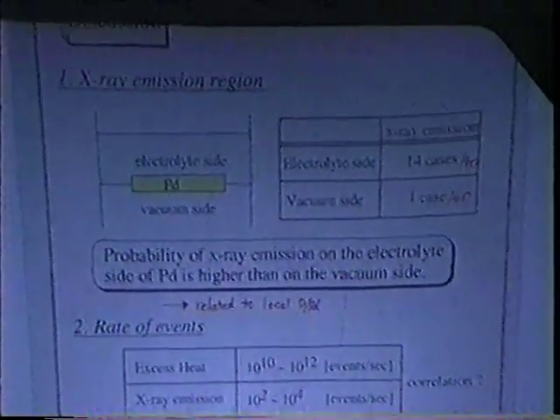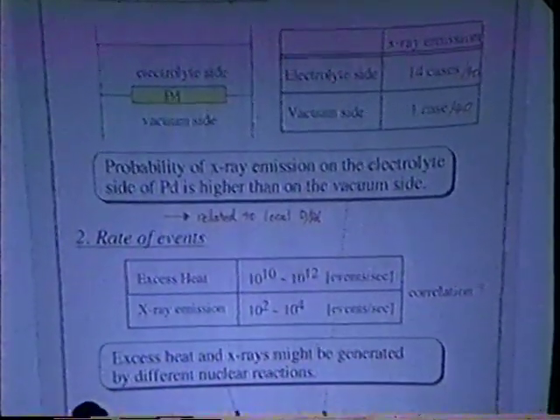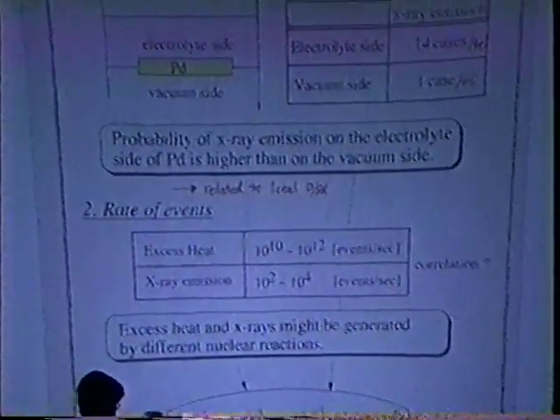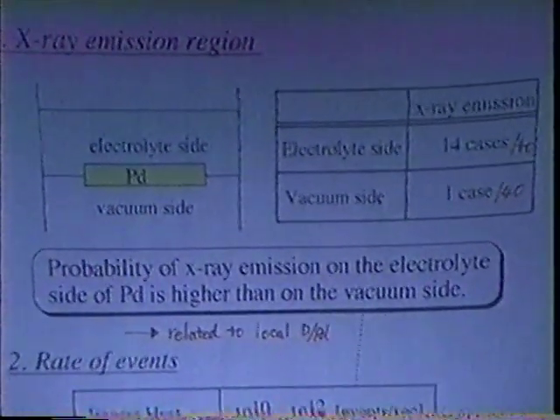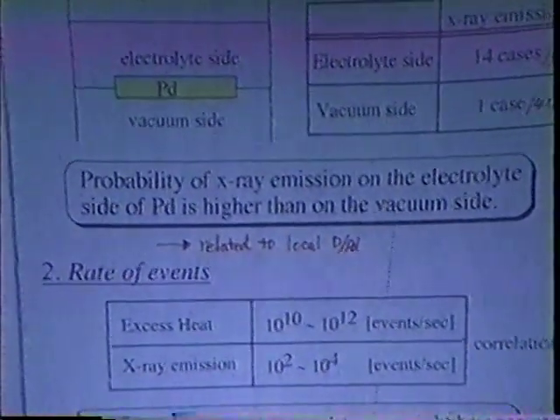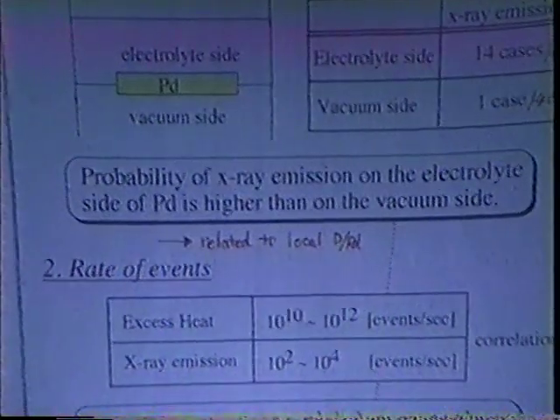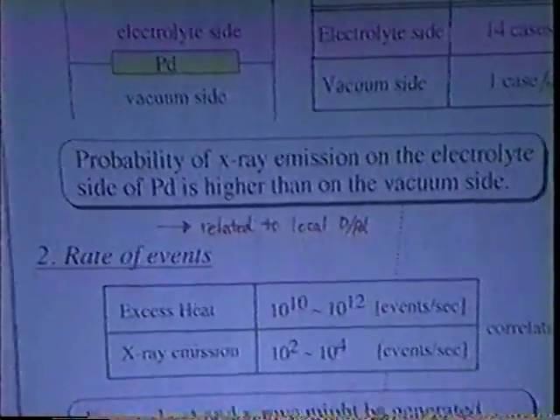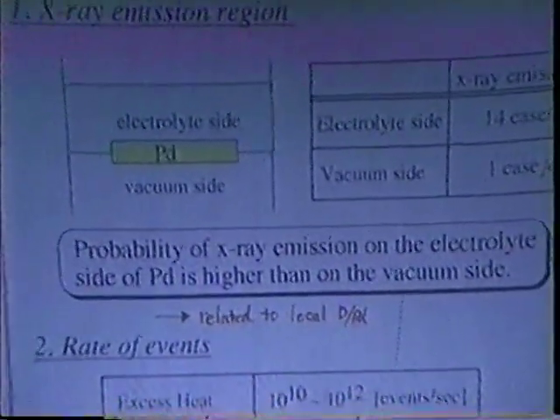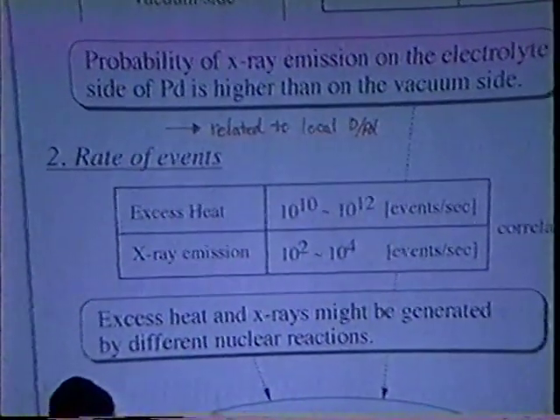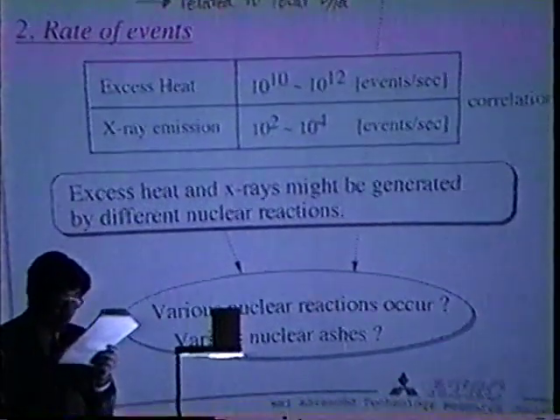Next, I would like to discuss on the experimental results we have obtained so far. The first point is on X-ray emission. We have experienced 14 times out of 40 that only electrolyte side X-ray detectors show the significant increase of the X-ray counts, though X-ray detector in vacuum chamber did not. On the contrary, only one case X-ray was considered to be emitted from the vacuum side of palladium. This one is